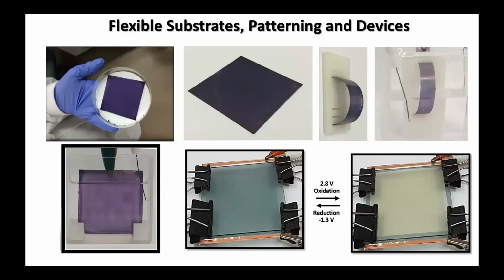Here are another few examples of films that have been prepared in our laboratory. You see here samples of films on ITO or on flexible substrates, metal oxide, ITO and PET. You can bend those films, and you can do that many times. The film is not affected by the bending. However, after several bending cycles, the ITO, the metal oxide, actually started to degrade. And here you see an example of such a bent film being switched in an electrochemical cell.